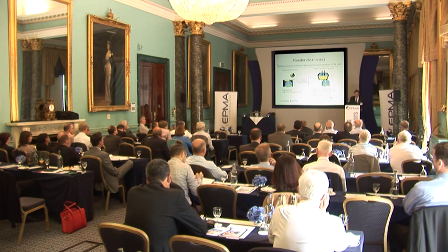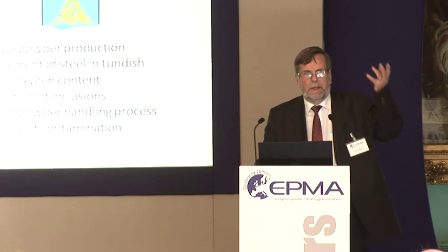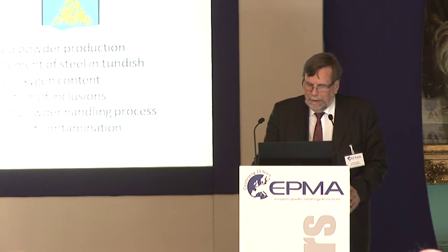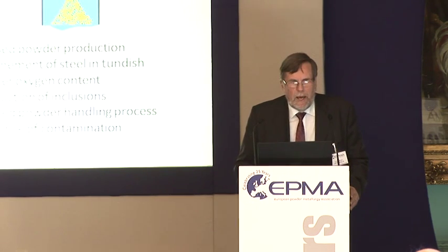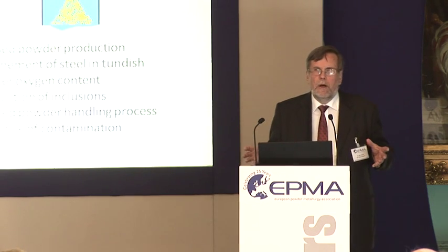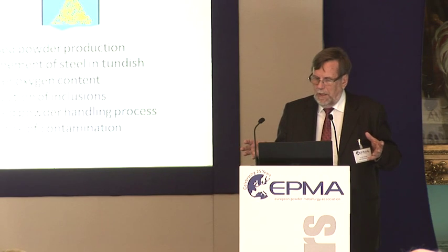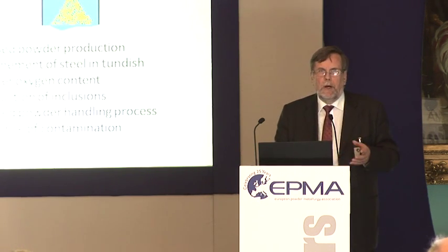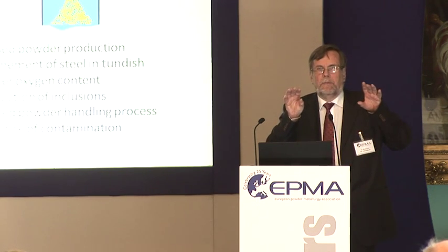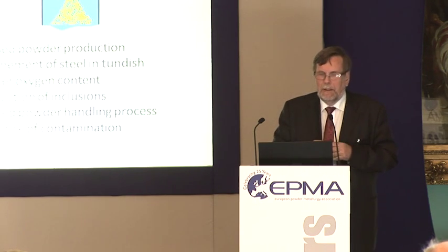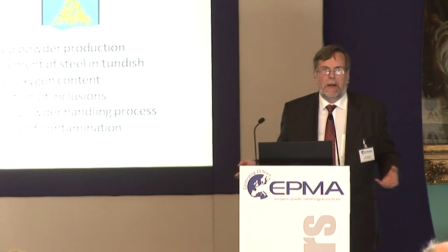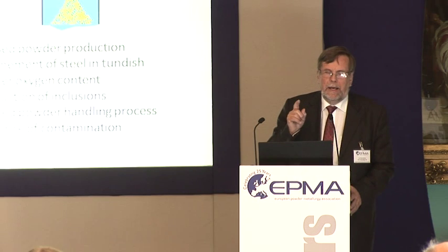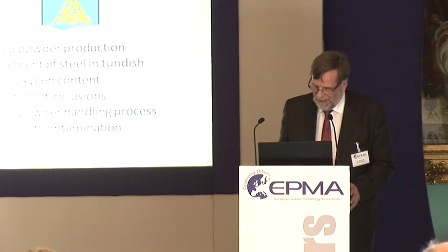The traditional process originally was to have a small tundish and fill it frequently, atomize and fill it again. This meant risk of exposure to air and high risk of contamination, and also the temperature in the tundish went up and down. With the modern process, for example, the most modern plant in Söderfors, you have a closed powder production. The tundish contains the whole charge, 5 to 8 tons. You do some refinement in the tundish, you get very low oxygen content. You have a heating system in the tundish, so you get exactly the temperature which you want, and you collect the powder without exposing it to air. And then you get very low contents of exogenous slag inclusions and virtually no surface oxides.